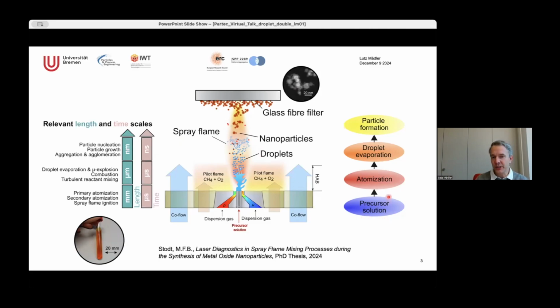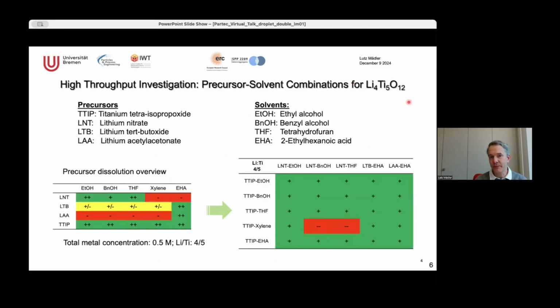And it involves different aspects: the precursor solution, the atomization, the evaporation, and the particle formation. And it's different lengths and time scales we're dealing with. But today I want to focus a little bit more on this solution here. And as I said, we make, as an example, lithium titanate. And this lithium titanate consists of lithium and titanium. And so in that solution I just showed you, you need a source of titanium and you need a source of lithium. And now it's a question what you put in there.